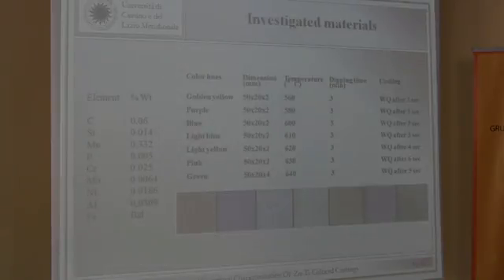This is a traditional hot-dip galvanizing coating. In our case, we use an addition of titanium, and here you can see the presence of different surfaces with different colors. This is not a painting, it's the real color of the coating. You have golden yellow, purple, blue, light yellow, pink, green, and so on. These are the differences between this coating with respect to the traditional coating.